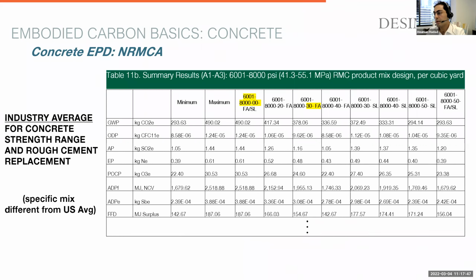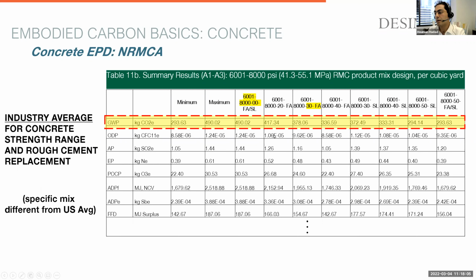And they do that by having different classes of strength for concrete, and different cement replacement. So was it up to 20% replacement of fly ash? Was it up to 30%, 40%? Was it more or less? And they associate one average number to every one of these categories. And these numbers are very important because eventually any of the LCA software working right now in the United States mostly relies on this data for the average global warming potential for concrete.